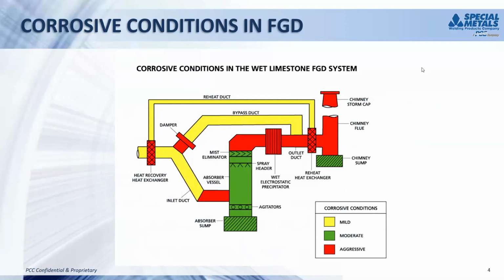The next slide shows the corrosive nature of the various components within the FGD system. The reaction tank, where the gases are mixed with the slurry, because of the wet nature of that, is only moderately corrosive. But the drier parts of the system, where there's condensation and formation of acids, are much more aggressive. These are the red zones. So the inlet duct, the outlet duct, and the chimney flues are the areas where we most often encounter corrosion and where the higher nickel alloys are required.